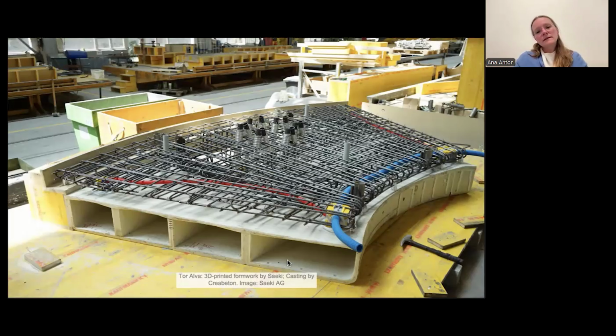You can also see that these precast elements accumulate all the functionalities of the column itself. It has to be heavily reinforced. It has ducts for electricity and light. It also has this interesting part of producing voids with the inclination of the columns that come on top to make sure that the rebar, which in some cases is 6 meters long, can fit from the top to the bottom in a continuous piece.